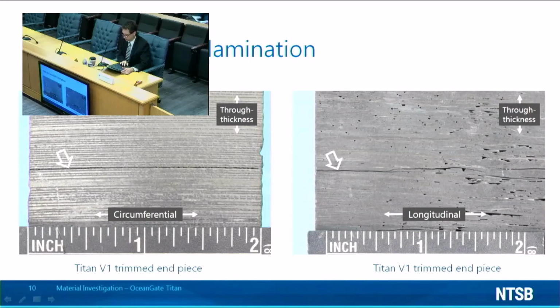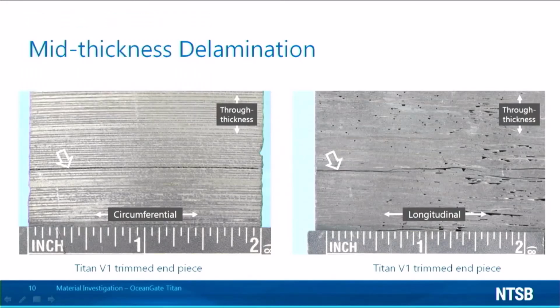One notable delamination was located about mid-thickness and is shown from different directions in these two images, as indicated by the white arrows.